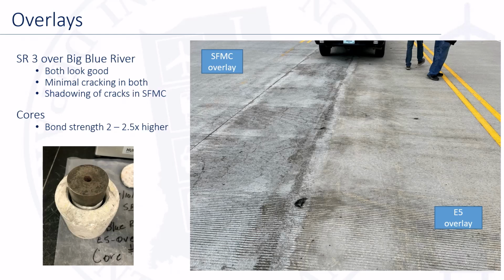And we've taken cores. We've noted that the bond strength has been 2 to 2.5 times higher. But this is still a new product, going on 3 years, so we've only had a few freeze-thaw cycles. So we're still doing chloride testing. Purdue is testing daily on this material, and I think Robert's probably going to get into that a little bit as well.